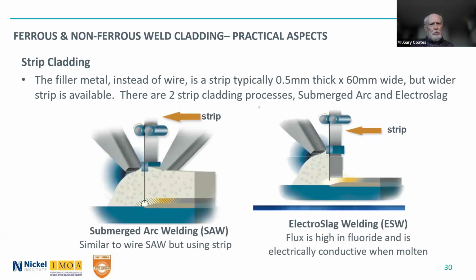Going to briefly talk about strip cladding here. So instead of wire, you're using a strip. Typically, it's 0.5 millimeter thick and 60 millimeter wide. Wider strip is available. There's really 2 main processes. One is submerged arc and one is electroslag. The subarc welding is like using the wire subarc, but using a strip. The electroslag welding uses a special flux that's high in fluoride and electrically conductive, and you get very, very high deposition rates with that.